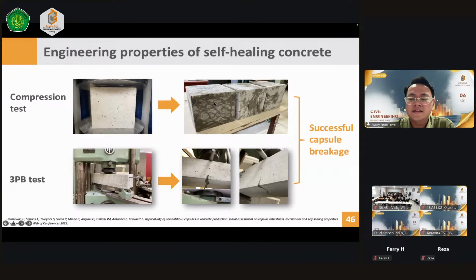The concrete itself will generate a lot of cracks due to the high compression stress. But due to this stress, the capsules inside will break, releasing all the sealing agent into the micro cracks, into the pores, into the hollow. So that is why you see there was a huge formation of the wet area, and this represents that the sealing agent is releasing via the cracks. Because of what? Because the capsule broke inside that specimen.